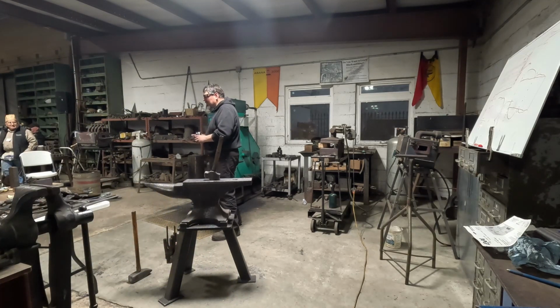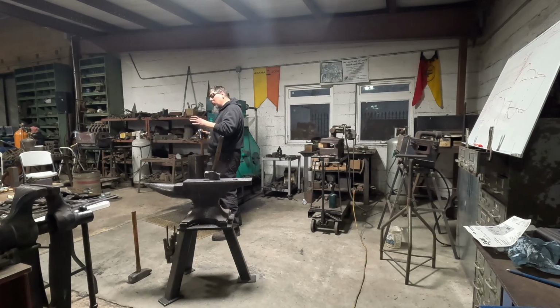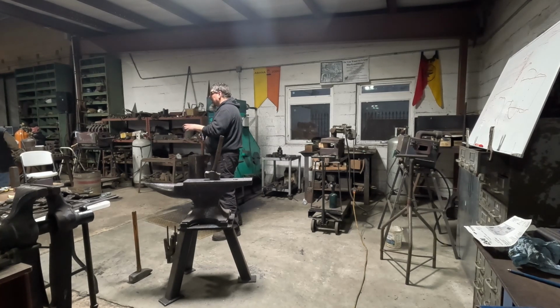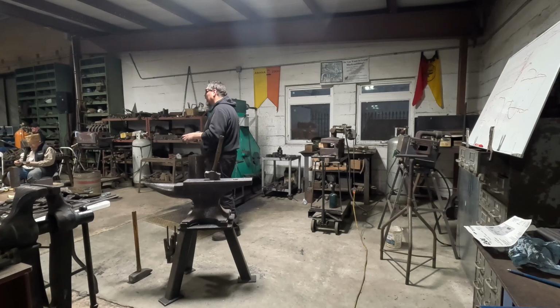The only time we see sulfur used in a positive way, at least in the steel trades, is where you increase the level of sulfur and also increase the level of manganese so that you, in the end, have a lot more manganese sulfides present. And that gives you some benefit to the machinist, especially years ago when people did a lot of screw machine work instead of the CNC machining we use today, where they have lots of form tools. So you're engaging a lot of area along the cutting edge to plunge in to create some unique geometry. Having what they call free machining steel was really helpful.